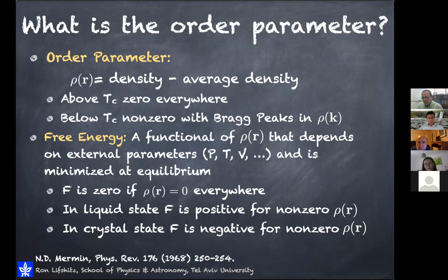Now, the interesting question here is that when we go from the liquid phase to the ordered phase, we're taking a phase which has a lot of symmetry, and because the free energy describes that phase as well, the free energy has that symmetry, but the state that minimizes the free energy has lower symmetry than the free energy itself.